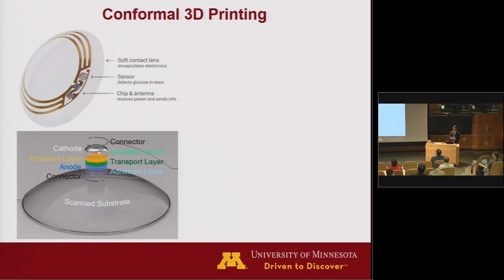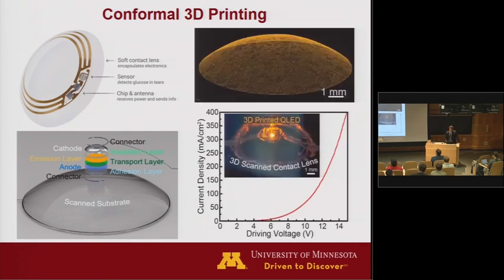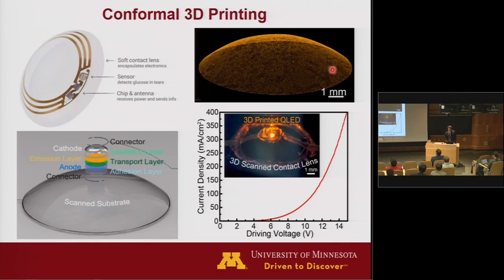It's difficult to take a semiconductor from its rigid planar format and merge it onto a three-dimensional soft biomedical device like a contact lens. But again, because our 3D printing process is additive, we can deposit the device layer by layer on the surface of the biomedical device or within the biomedical device in a way that can't be done with any type of traditional microfab. And the trick here is we 3D scan the contact lens. We get the exact geometry of the lens, and then we conformally print these semiconducting-based devices onto the contact lens.